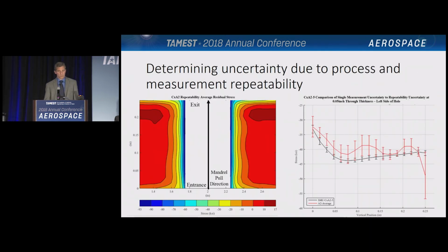So these next couple slides cover work we performed recently in support of the uncertainty quantification and analysis aspects of ERSI. Measuring residual stresses due to cold working is a complicated process. What is actually measured is the displacements on the scale of microns, which are then analytically turned into stresses. And there are many potential sources of error and variability, so we've done work to determine the single measurement uncertainty, shown in black in this plot, and the repeatability uncertainty of the measurements, shown in red.